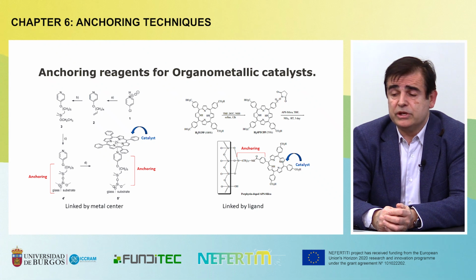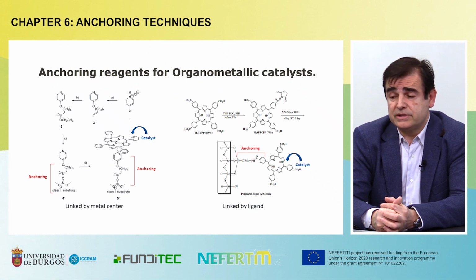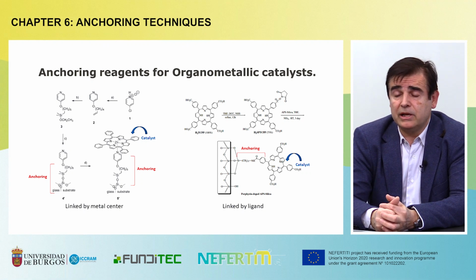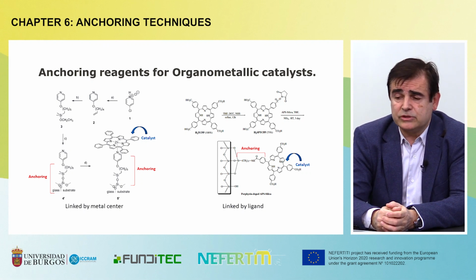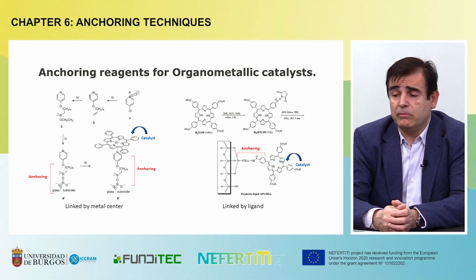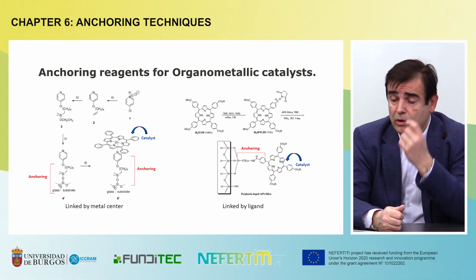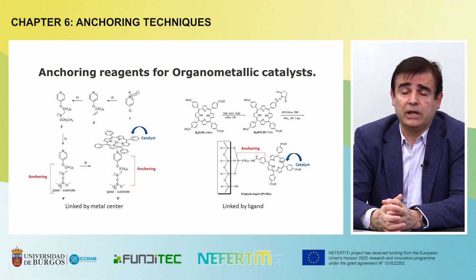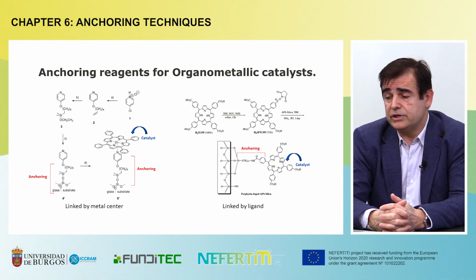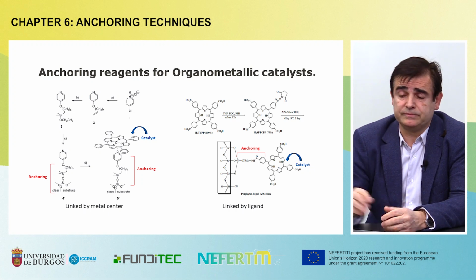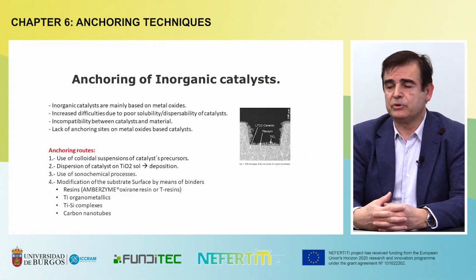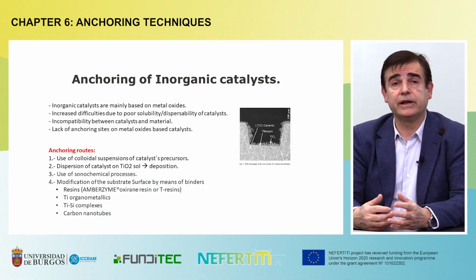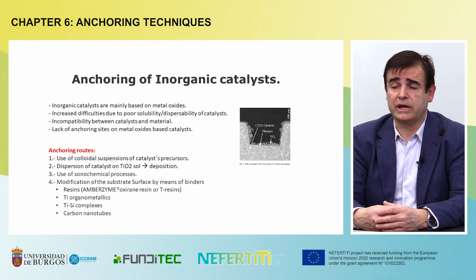The difference between these two types of anchoring is the strength of the bond achieved, the latter being more labile than the former. As a rule of thumb, stronger covalent bonds should be preferred. However, this is not always possible, and anchoring has to be undertaken by simple coordination in a vacant position of the metals. The case of the deposition and anchoring of catalysts of inorganic nature presents some particularities.